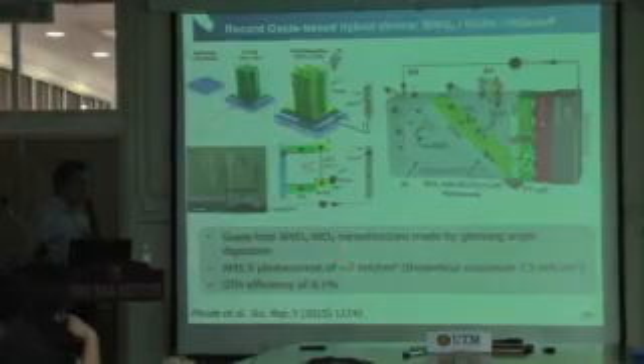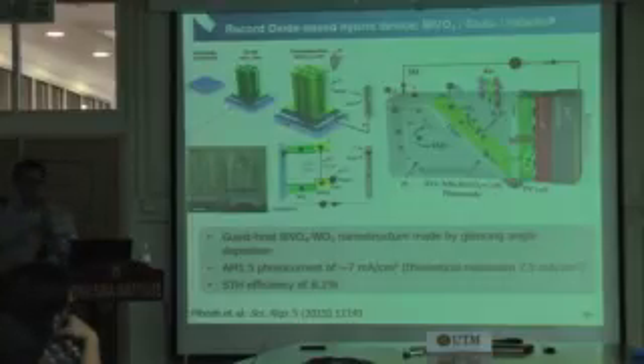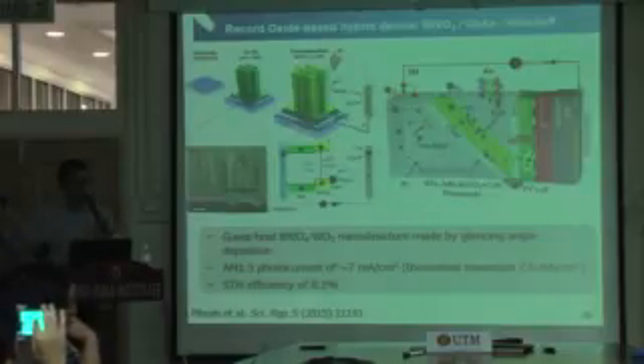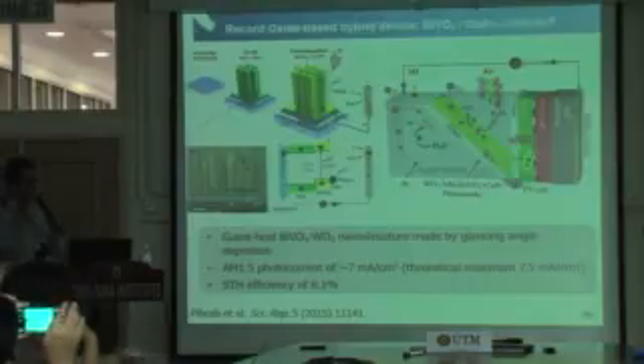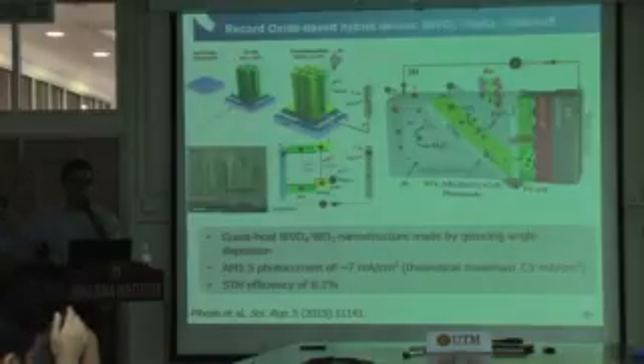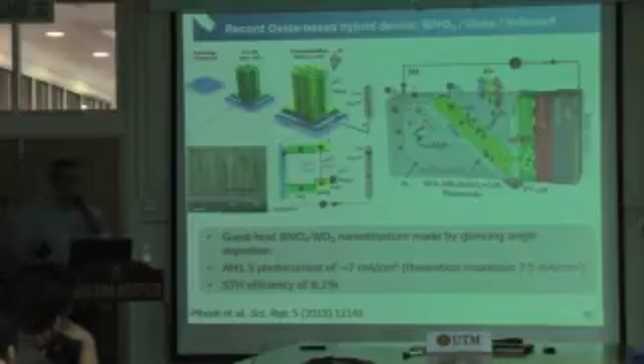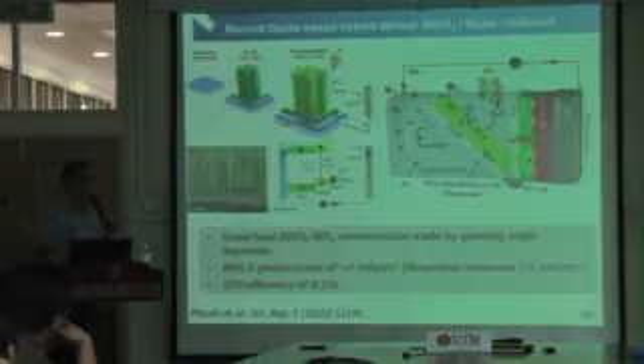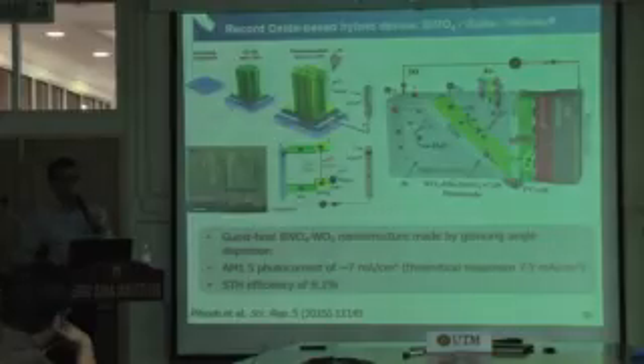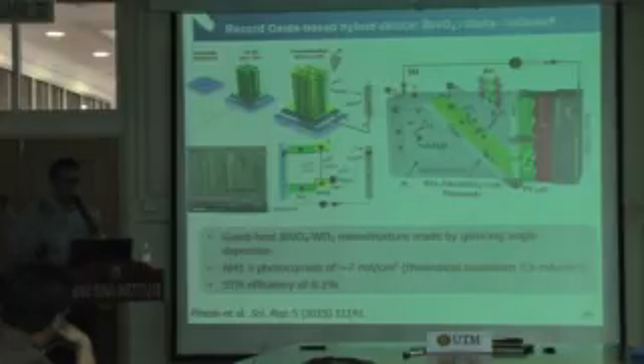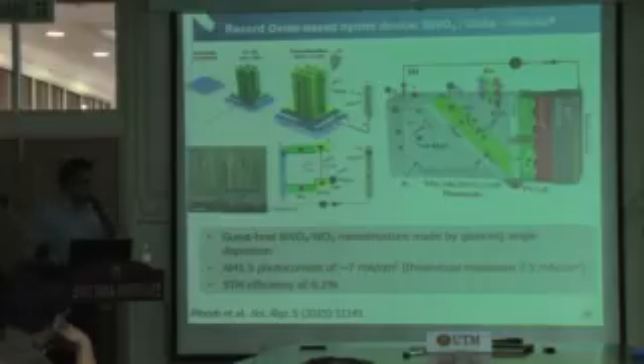On the one hand, we're a little bit disappointed that this was not us, so this was improved in Korea. But on the other hand, it actually makes us feel better because our colleagues in the field are actually working on different classes of materials, not metal oxides. For example, III-V semiconductors, which are really good semiconductors. Often they look down on metal oxides because they say metal oxides have poor carrier properties. So you will never be able to actually collect the current. I mean, you have polaron transport, a type of hopping, so it's very slow, carrier mobility is low. You will not be able to get to the highest performance. But this actually beats it.